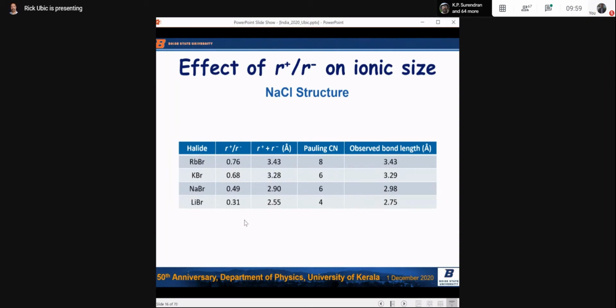It's because as the ratio goes down, the anions are getting closer and closer together. And Shannon's rules were developed assuming neutral hard spheres. Atoms were marbles, basically, right? The problem is atoms aren't marbles, and the outsides are not hard, and they're not uncharged, right? You've got a cloud of electrons on the outside of your atoms. They're the ones that are going to be touching, and they're not going to touch, right? So if they approach too close, they start to distend, and it effectively makes the anions, and the cations too, look larger than they are. So you get larger bond lengths in reality than Shannon would tell you you would have.